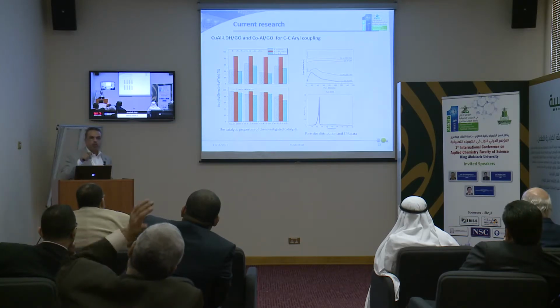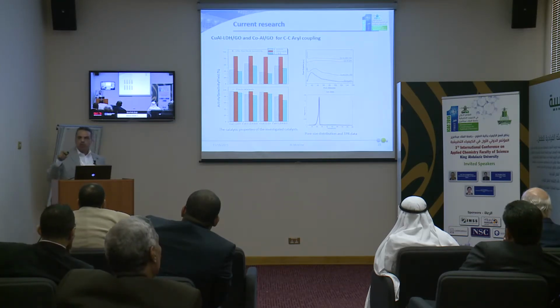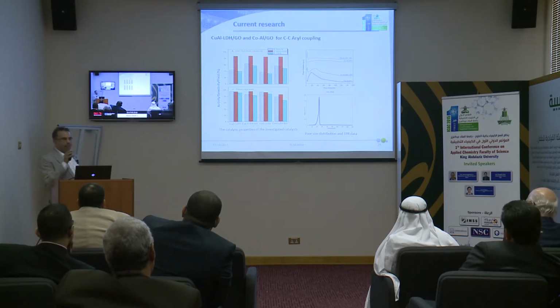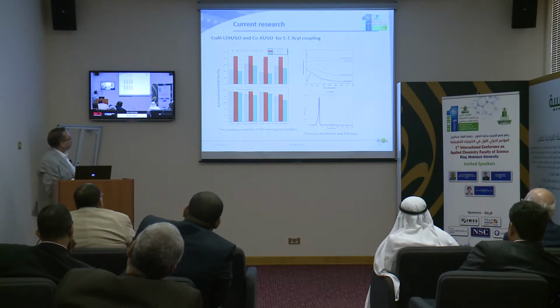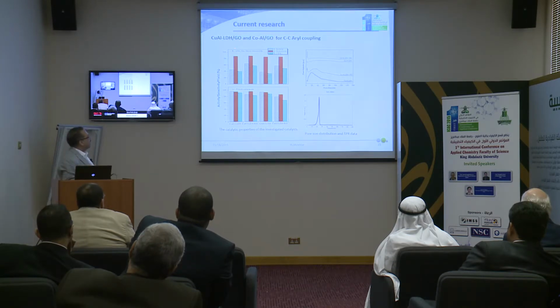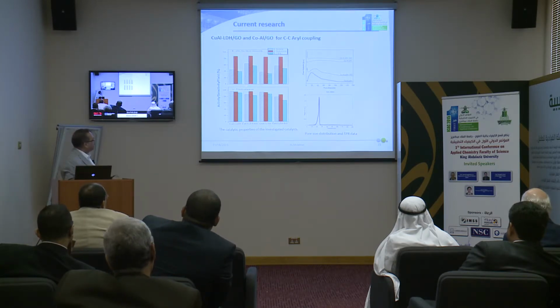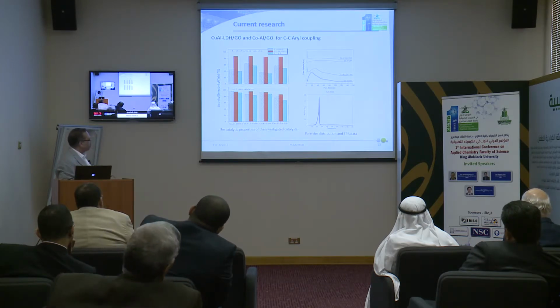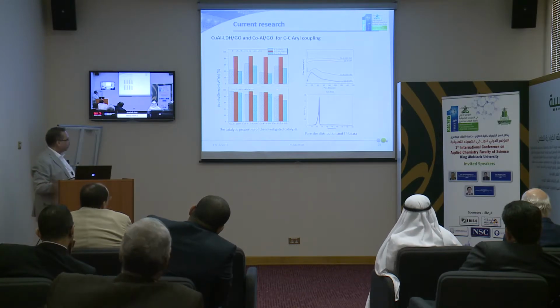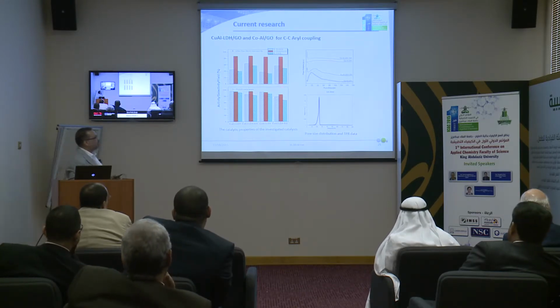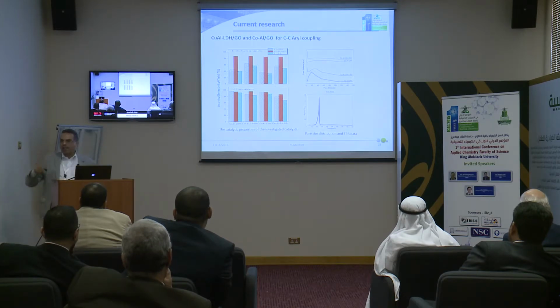Originally, cobalt and copper substitute magnesium, isomorphous substitution of the magnesium in the cationic sheets without any change, without any impurities. This means just removing magnesium, adding cobalt or copper in this sheet, but they have two different properties. Copper itself, without graphene oxide support, gave a higher percent yield with the fresh catalyst. For the fresh catalyst, we could find that the copper is better than copper supported on graphene oxide, better than cobalt unsupported, better than cobalt supported. But what happened if we do the reaction and reuse the catalyst many times?